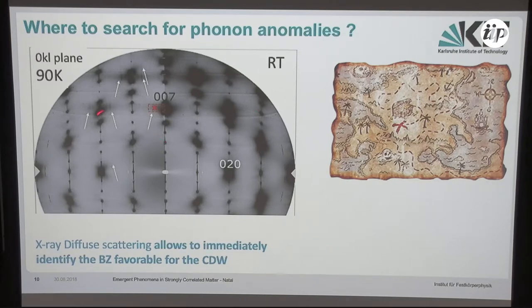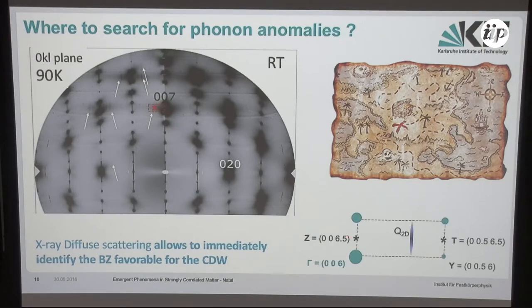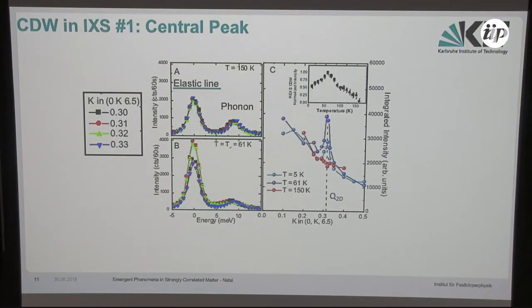Actually, this kind of map I find quite remarkable, because this is basically a 10-minute experiment, and yet it took 30 years to observe the charge density wave. It's a bit more subtle than that. You really had to get the latest generation of detectors, noise-free with a very high dynamic range, because you have 6 to 8 orders of magnitude difference in intensities between the Bragg reflection and the CDW satellite. But now it exists, it works, and it's very useful. So we placed ourselves here in the reciprocal space, and we are going to just scan from that set point here at 6.5 across the 2D wave vector.